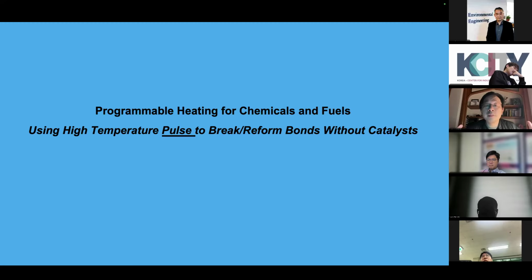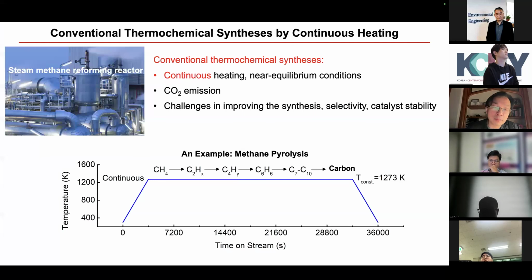For example, you can 3D print a reactor so that you can have plastics flow into the pore structure, and as they flow, they get heated up, and you are using the heating to break the bond and to reform the materials. In this case, we don't use any catalyst. Catalyst usually is a problem for stability, and usually a problem for cost. So here, I think our reactors will basically have better stability. So this is actually what industry is doing right now, yeah, right.